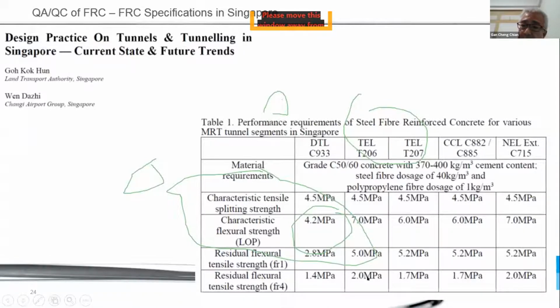Why this is so is because at the beginning, fiber concrete was designed as plain concrete, so they didn't take into account the contribution of fibers. But in later projects, they try to take into account some contribution of fibers. As a result, you need higher FR1 and higher FR4 numbers. FR1 is connected to serviceability limit state designs, which means durability design is connected to FR1, and FR4 is connected with ultimate limit state design. So when you talk about bending moments and you want to have higher bending moments, you need a higher FR4.